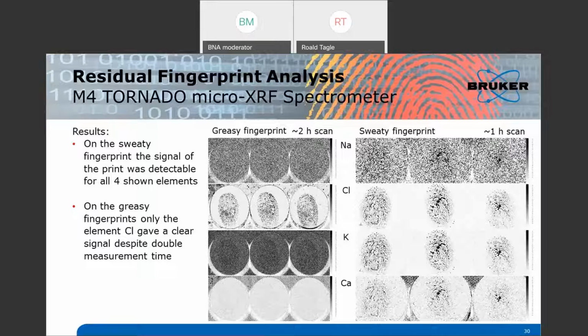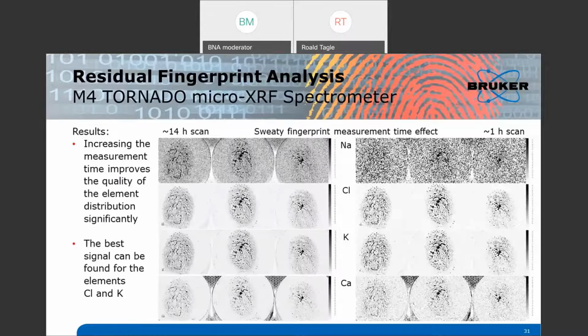So basically, it's an element that gives quite a strong contrast, because its contrast has two factors. One is the amount of this element in my sample with respect to the surroundings, and the other one, which we need to take into consideration, is also the sensitivity of the instrument and the settings of my measurement. So as you see here now, once we know that we are able to detect that, we will now focus first on the sweaty fingerprints and how to improve the contrast.